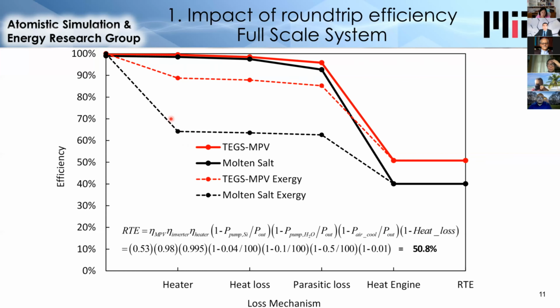On the other hand, when you're only storing around 600 degrees Celsius, you lose 40% of the usefulness just from that first conversion, which limits what you can do downstream. And this is one of the reasons that the TEGS high temperature system is so appealing.